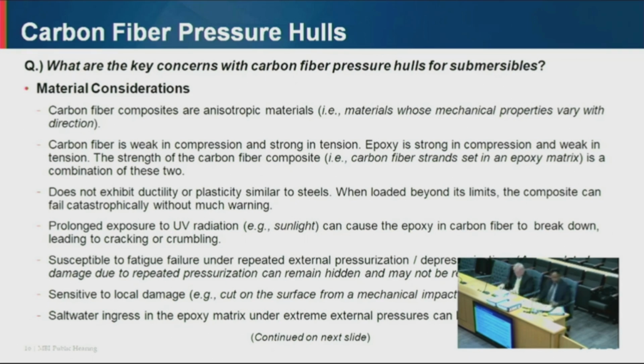So the next thing is carbon fiber composites are sensitive to local damage. So if you have a cut on the surface from a mechanical impact, this can grow to form a crack, which can lead to failure of the pressure hull. Okay, so it's very important to protect carbon fiber composite pressure hulls from impact loads.